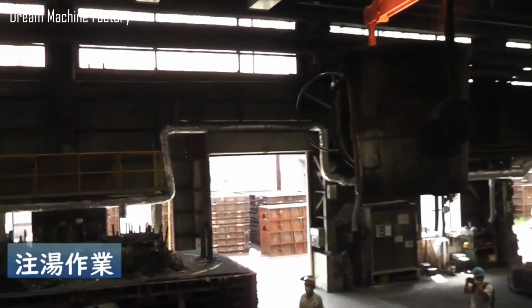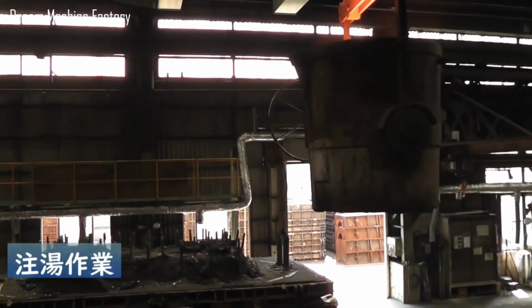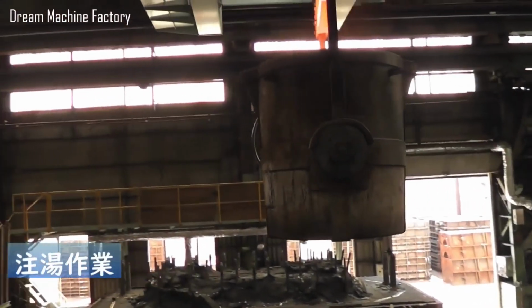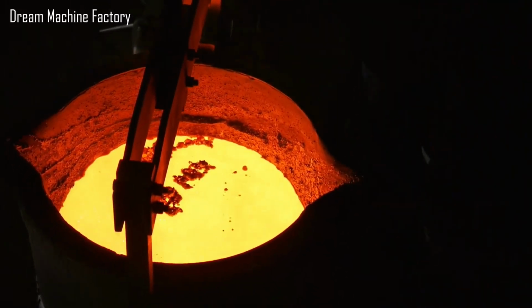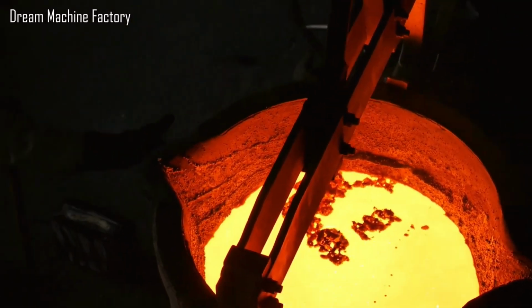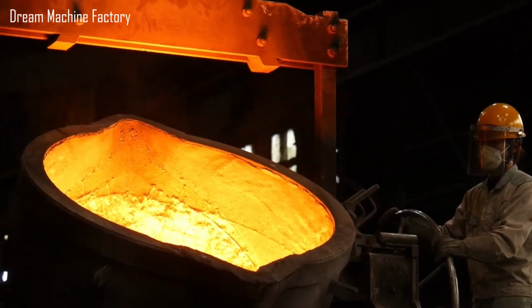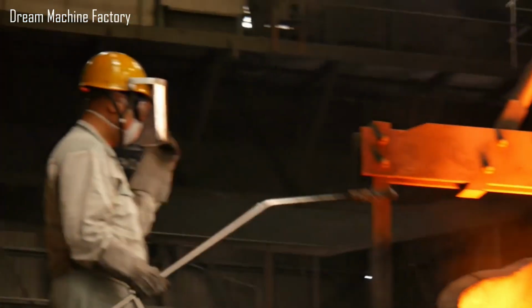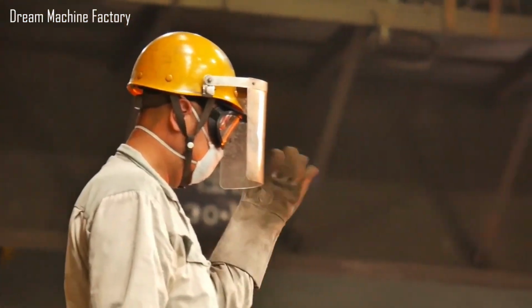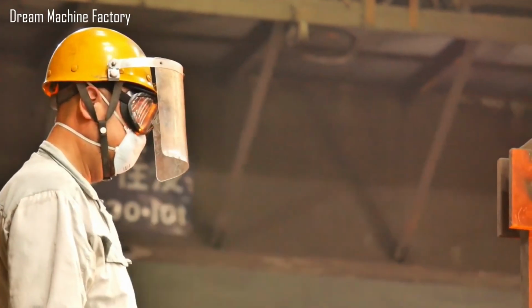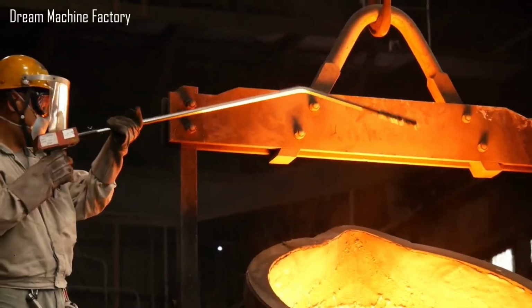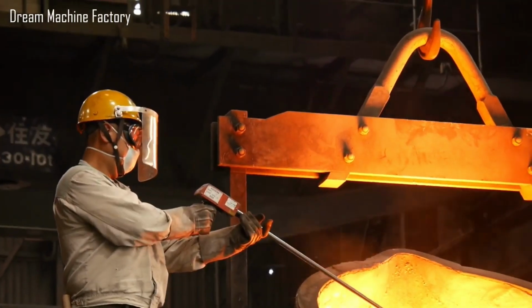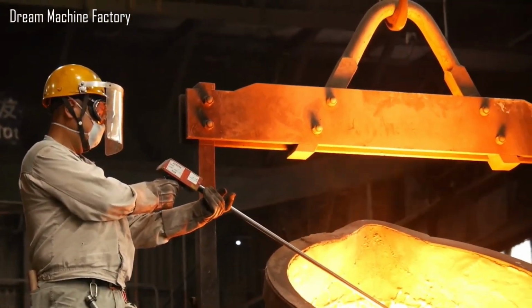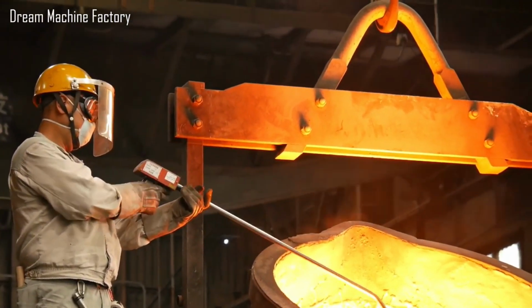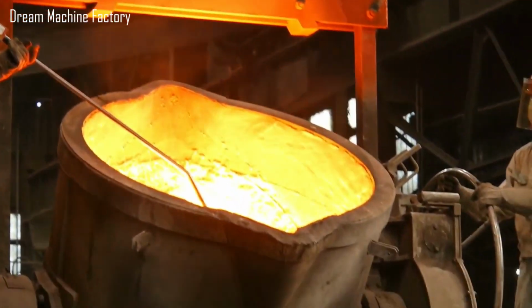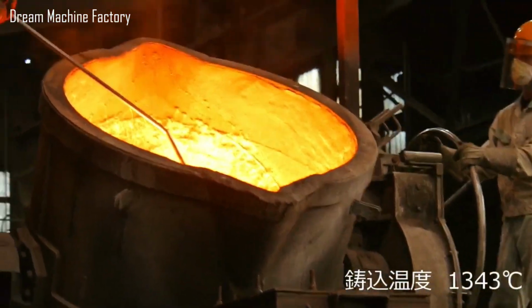The pouring operation is one of the most critical steps in the casting process, as it directly affects the internal quality, surface finish, and dimensional accuracy of the final product. In this process, molten metal is poured into the prepared mold cavity at a controlled pouring temperature of 1343 degrees Celsius. Maintaining this precise temperature is essential to ensure that the metal has sufficient fluidity to completely fill the mold without causing premature solidification, which could lead to misruns or cold shuts.